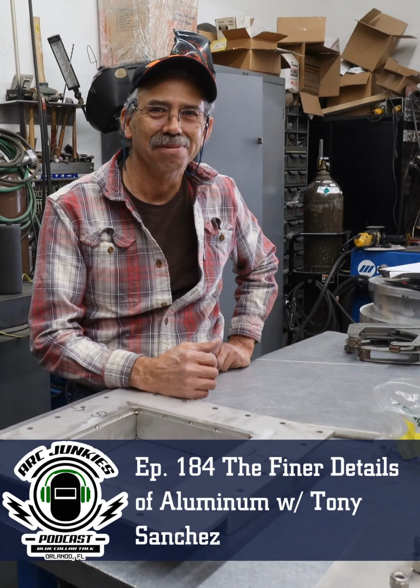My theory is usually if I have pinholes or something like that, I try to go a little bit deeper than that pinhole was to make sure I'm in there. And then if you're doing that repair on aluminum and you run it with a convex puddle, you almost always have pinholes somewhere on the edge of that puddle. They may be tiny sometimes, but if you're running a convex puddle, you'll have the pinholes. If you go to a concave puddle, you're pushing, and you're loading everything to the side. Your argon gas is not able to suck air underneath that puddle. When I'm running aluminum, I don't tip much, especially the heavier it goes. I'm straight down because I'm trying to keep that puddle there.